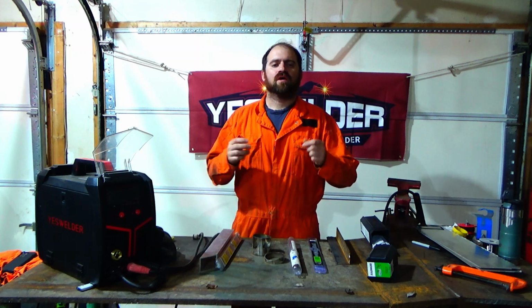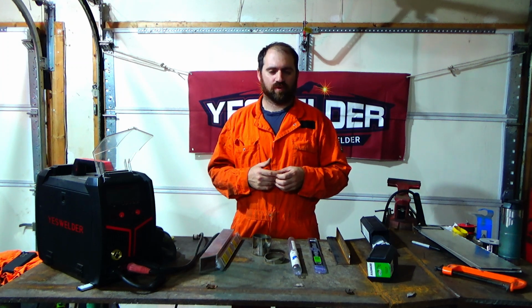There is also another rod that is called nickel 99 that works well too. Nickel 99 is at least 85% nickel and is more machinable and ductile, but it's not as strong as nickel 55. Nickel 55 is also more difficult to use. Now cast iron should always be preheated before welding, but when welding with the nickel 55 rod, it would benefit from a post-weld heat treat to minimize cracking. Nickel 99 is ductile enough in most home applications where you shouldn't really have to worry about a post-weld heat treatment. But with nickel 55, I definitely would.